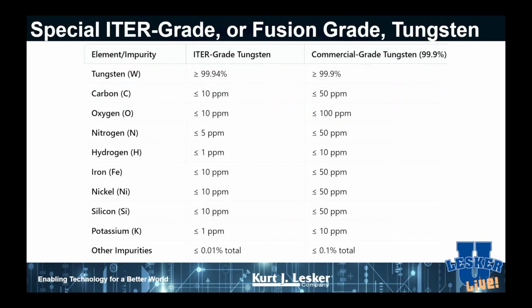Of course, there's now a sort of ITER-grade tungsten, and this is a super grade of tungsten, where the carbon's less. All of these things are in better, higher purities than you would normally see in typical tungsten. Things like nickel, which is sort of a bad actor, silicon, kind of a bad actor.